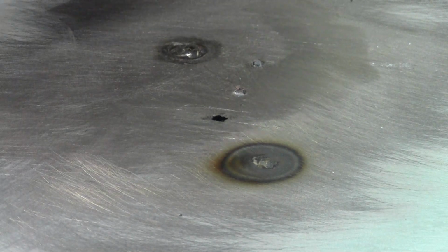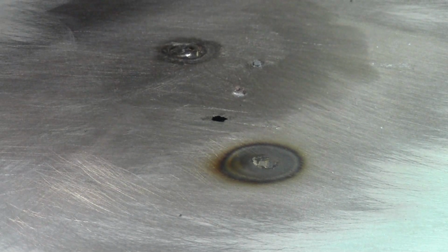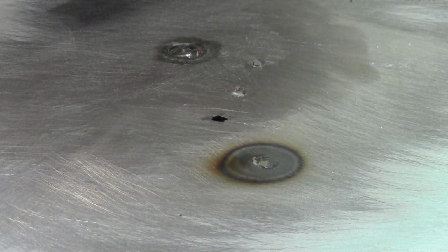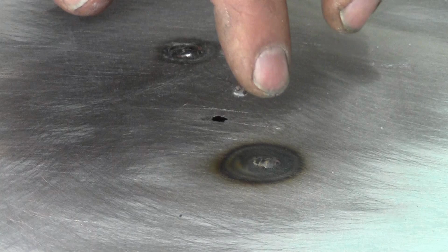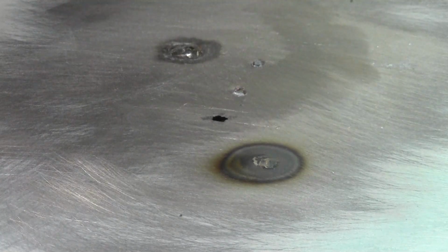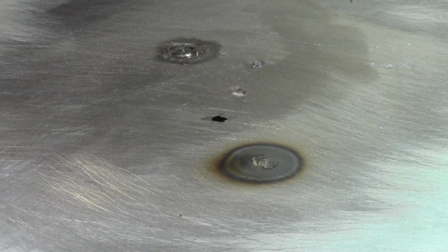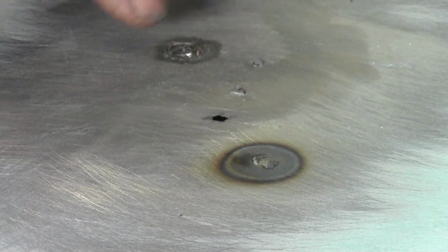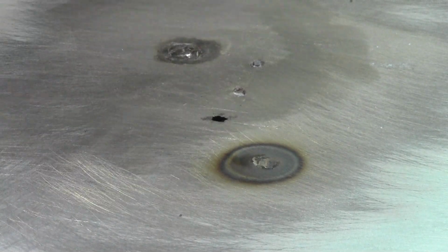The heat affected zone on the first weld here with the product, Heat Freeze, is much smaller than even with a smaller weld on a smaller pinhole. And the warpage is less, even though I welded more.